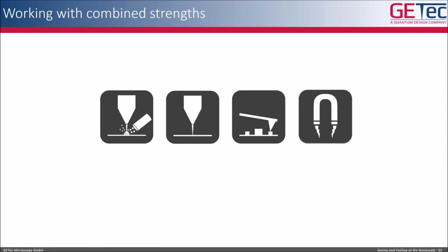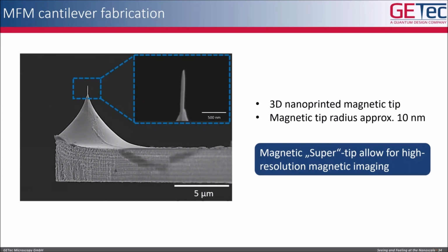Now I want to move on to measuring magnetic properties. I also want to briefly show you the type of cantilevers we use for these magnetic measurements. This is also a quite unique cantilever, since we're using the same 3D nanoprinting technique to create the magnetic tip. But now the tip is not made out of platinum, but out of a magnetic material—in this case, iron. We can 3D nanoprint these high aspect ratio iron tips on top of our silicon tips, which then enables us to create these magnetic super tips that allow for extremely high resolution magnetic imaging.